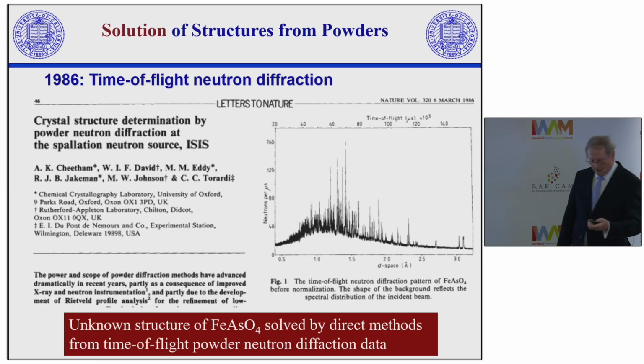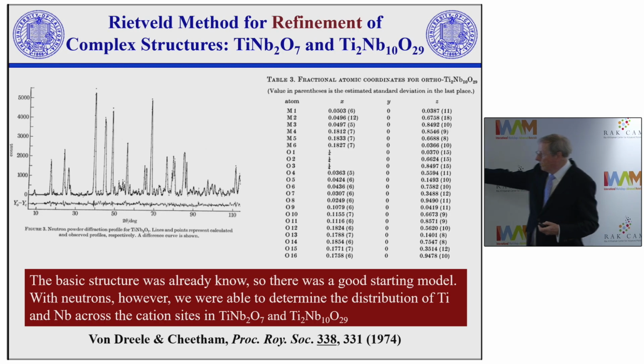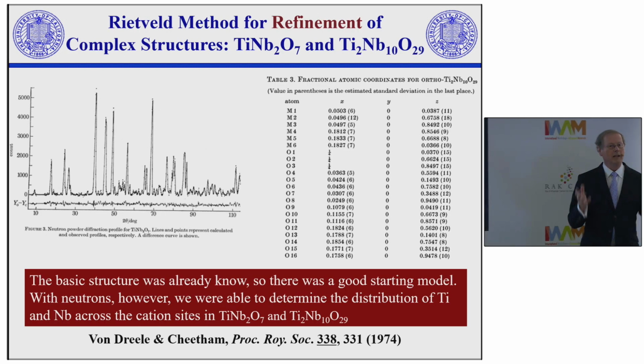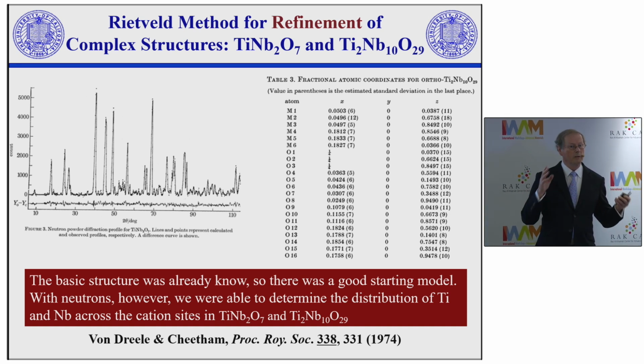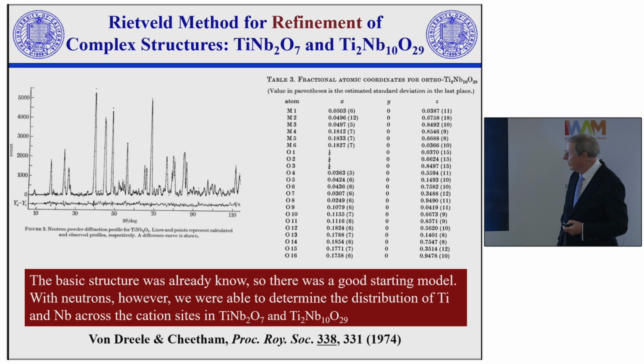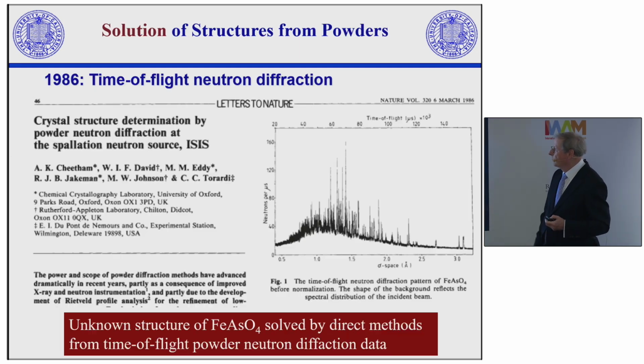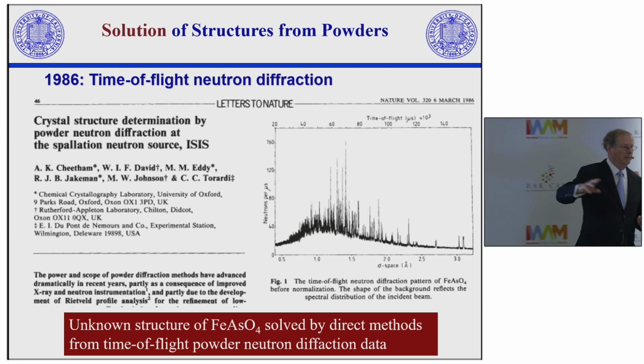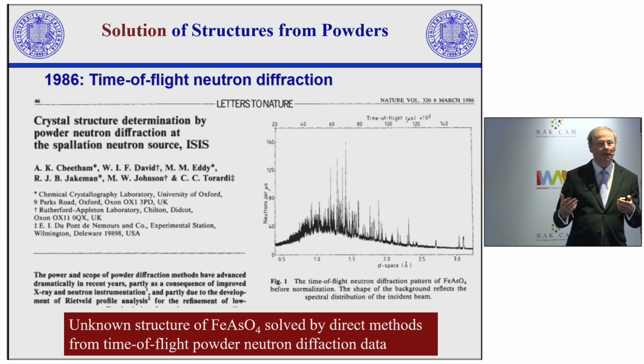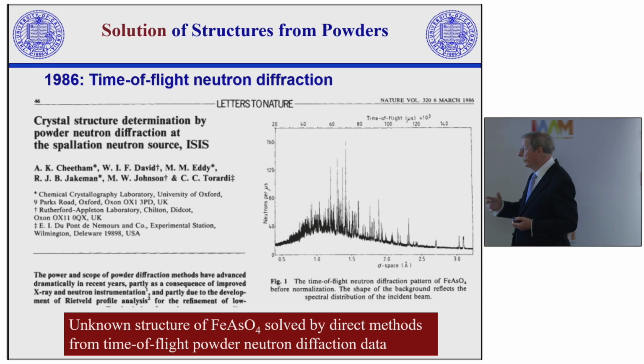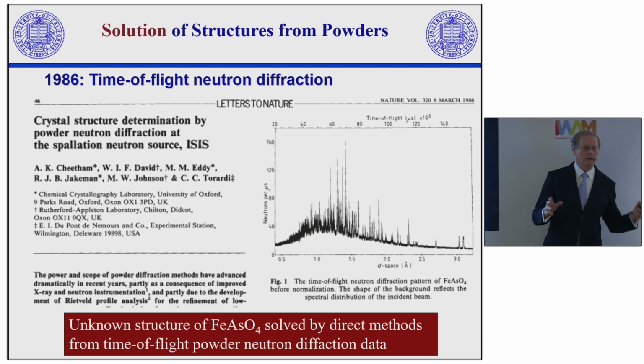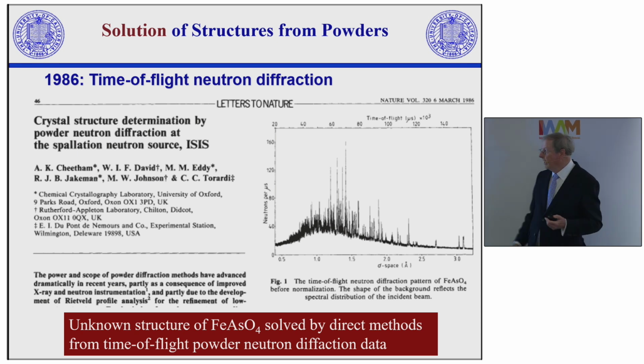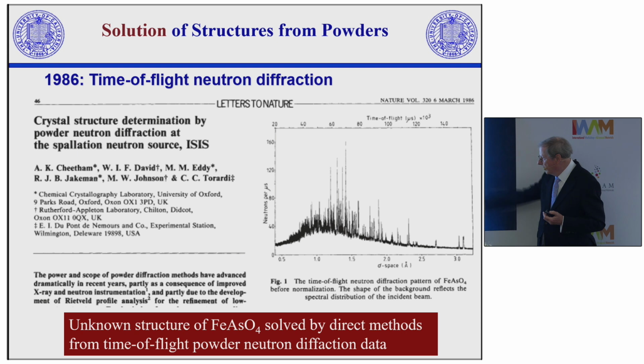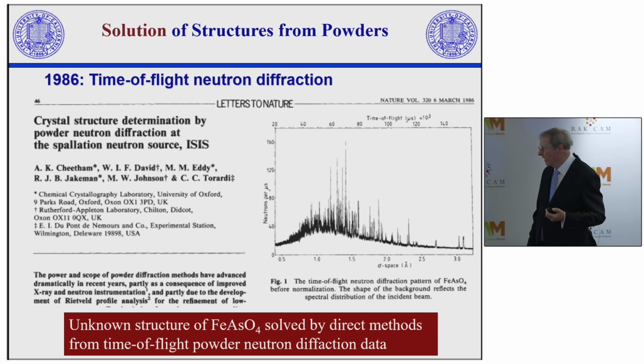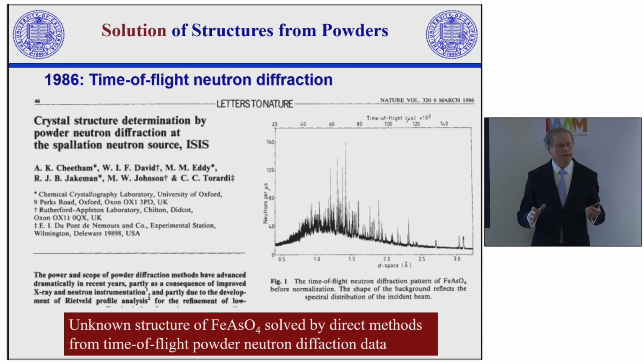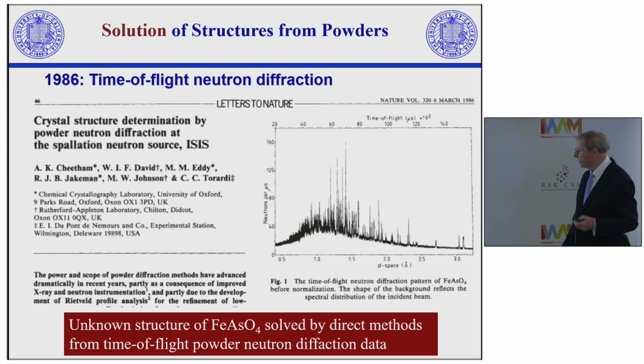So if we look at that previous slide, what we've done here is refined and improved the solution to a known structure that the X-ray people had done. About a decade later, just as a segue, we showed that you could use these powder techniques, and this might be one of the reasons I'm here talking to you today, because we showed that you could not only refine structures, but you could also solve totally unknown structures from powder data. And we did it both with very high resolution neutron data, which I'm showing here, and also with very high resolution synchrotron data as well.